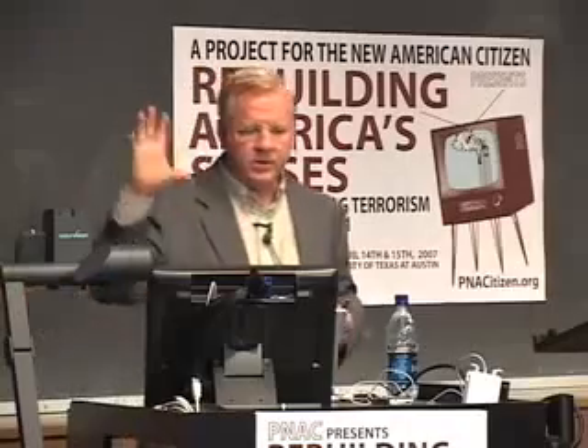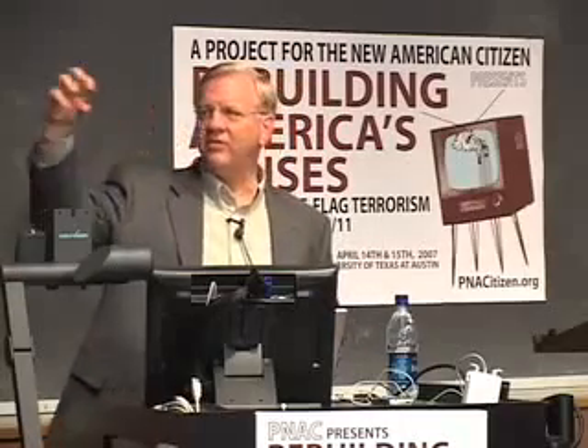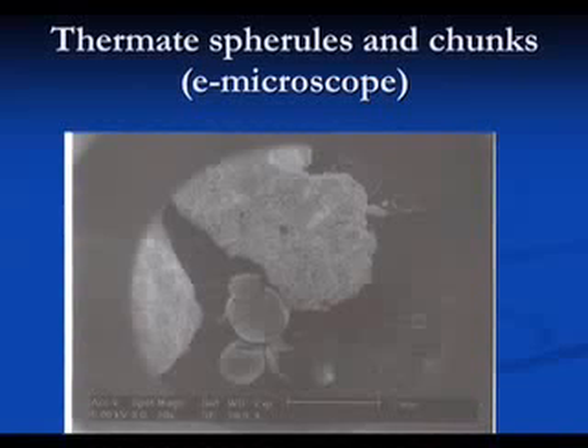Now this iron, plus whatever else, like sulfur, aluminum, will form a sphere because it's hot, and then it has surface tension, pulls it into a ball, and then as it flows through the air, it cools off and retains that spherical character. Now, this is just with a camera, with macro, and you kind of see some spheres. This is 1 millimeter, so these spheres tend to be small from thermate. This is looking now with the electron microscope. You see these spherules. I'm just going to call them spheres or microspheres.